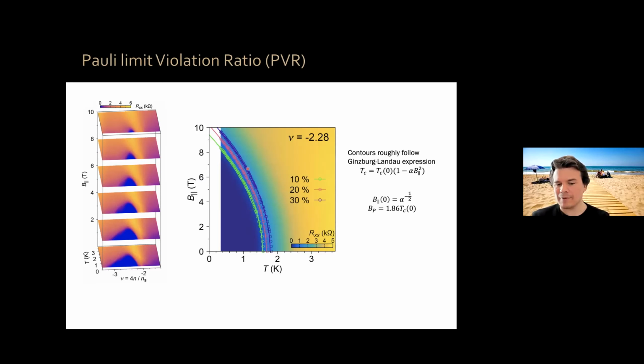These contours happen to be quadratic in magnetic field. And B Pauli is 1.86 times TC. So whichever threshold we want to take for TC, we can take it, and find what is the Pauli limit. And the Pauli limits are here for these different thresholds. Which means that we're violating the Pauli limit by over a factor of 3 at this particular density.